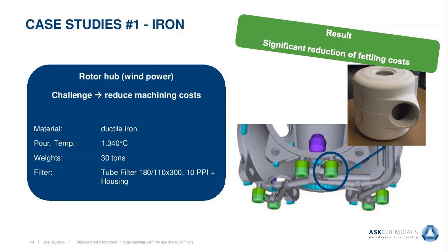Especially in the manufacturing of large castings, as I already explained, people must install big downsprues and runners, and in many cases, multiple runners are used. This can promote the generation of turbulence and consequently the risk of reoxidation within the molten metal. At this point, an improved, more consistent and safer solution for filtration was needed. We cast this one with 6 filters from the biggest size and also 6 housings, and the filtration was really, really successful in this case.